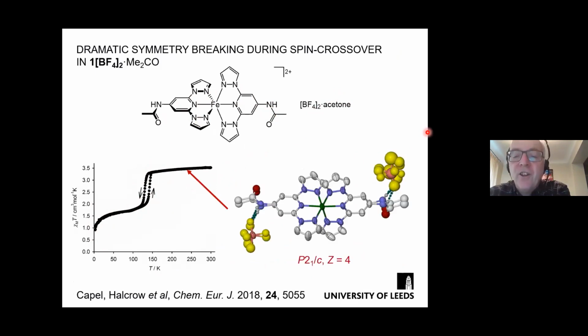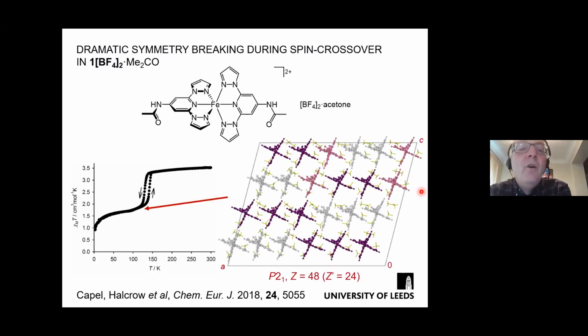And you look at the crystal structures, the high spin crystal structure is unexceptional. There's a lot of disorder here at the outside of the molecule, but the basic thing is there's nothing of great interest here. But the low temperature crystal structure, I should say that is the asymmetric unit of that crystal. 24 unique molecules in that asymmetric unit. Some of them are high spin, some of them are low spin, and these ones have a mixed high spin population at this temperature. And you count 1, 2, 3, 4, 5, 6, 7, 8, 9, 10 high spin, 10 low spin, and 4 which are mixed spin states.